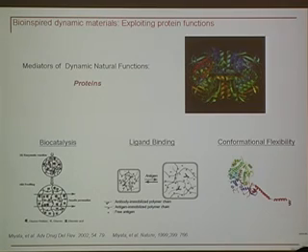That antibody and antigen, under initial circumstances here, are bound to form non-covalent crosslinks in a network, so the crosslinking density is initially quite high. If one then flows in soluble antigen to compete with these interactions, the soluble antigen binds the antibody, dissociating the antigen-antibody complex, and you get increases in swelling, which can be useful for drug release and other technological applications.